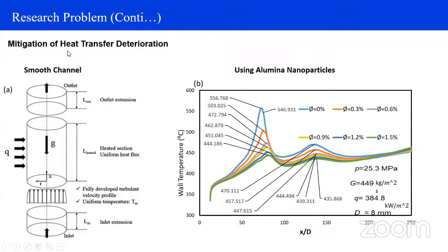Mitigation of heat transfer deterioration. Actually, the first peak and second peak: if this peak increases, then deterioration is increased because of sudden change in wall temperature. If wall temperature increases, there is a chance of leakage of the nuclear reactor or a blast. So our main task is to reduce deterioration. Like we can see here, the peak is high compared to the second line. The second line is lower compared to this line.